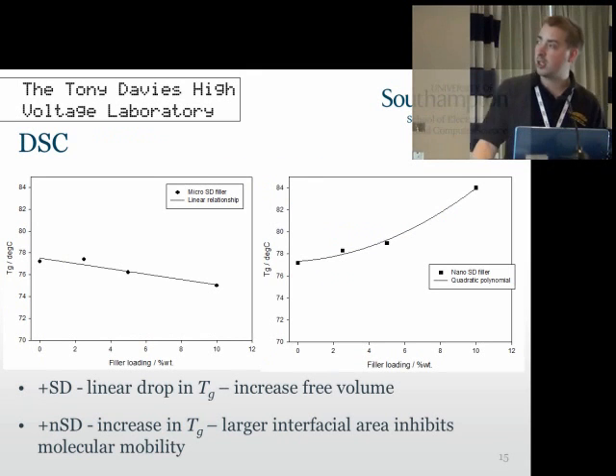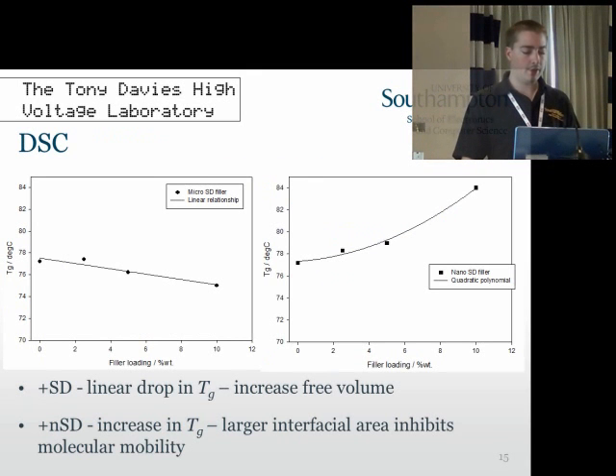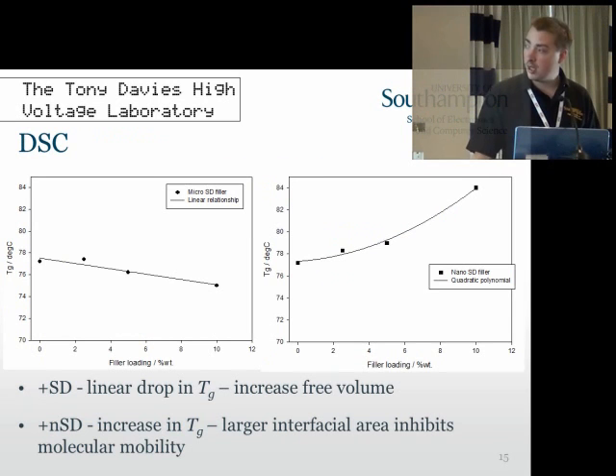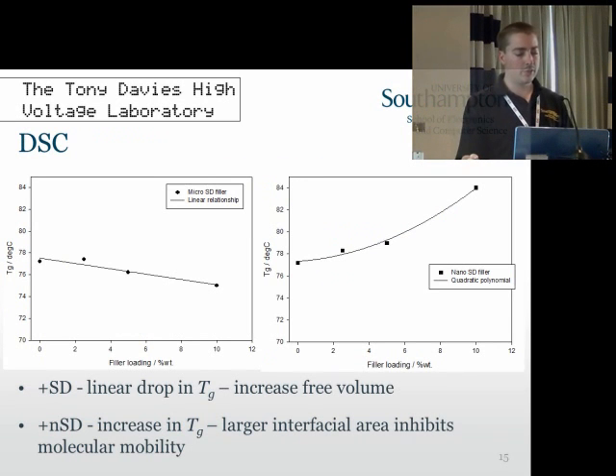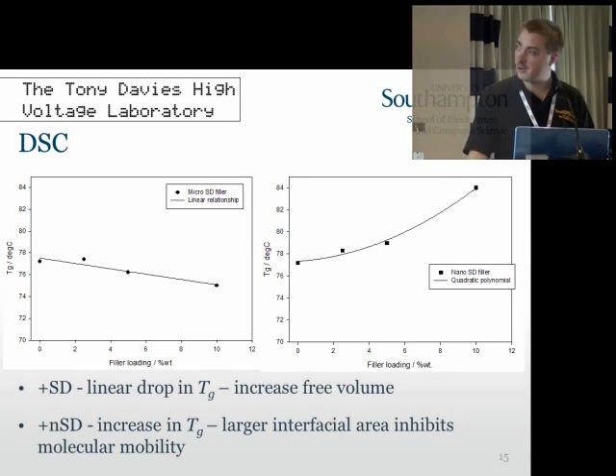Okay, so just having a look at the filled systems, the left-hand figure shows the micro-silicon dioxide filled system. And we can see that increasing the filler loading has caused a very slight decrease in the TG. Nothing major, but still within error and noticeable. This is mostly just due to an increase in free volume. Nothing really new to report there.